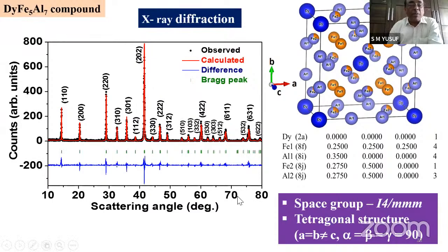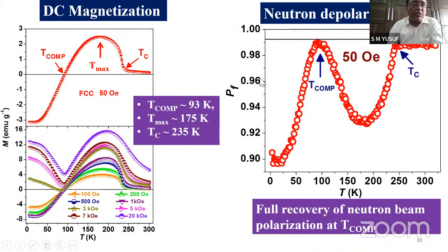And this is but what happened? Those oxide materials, in fact, in my lab, we tried to measure magnetoresistance of those either ferrites or perovskites, but resistance is so high that it went out of our measuring limit. But here we could do it, and this is the crystal structure. Here again we show that magnetization is changing sign, and we also show the field dependence. Very nicely we reproduce. This is not yet published. This is also again Deepak's work, my student's work. So magnetization changes sign with the field.